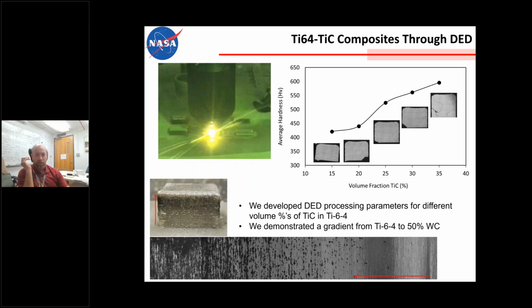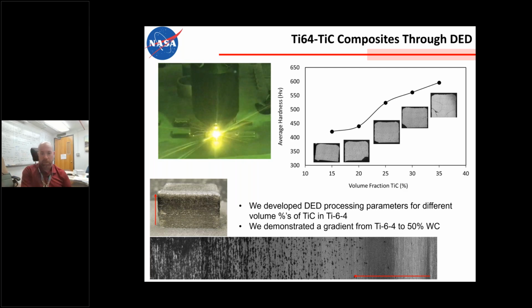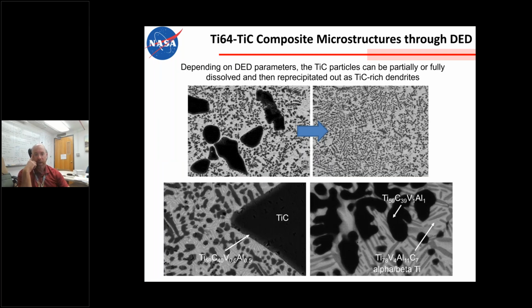So we're able to do functionally graded Ti to Ti-carbide alloys. With DED, you're able to control the melt pool to partially or fully dissolve these Ti-carbide particles to create metal matrix composites with really innovative microstructures. So here you see some micrographs of partially dissolved and reprecipitated titanium carbide in Ti-6-4 parts.